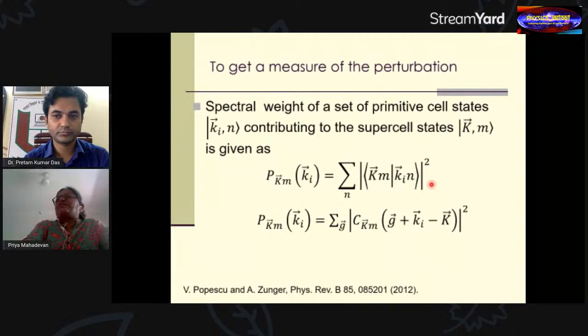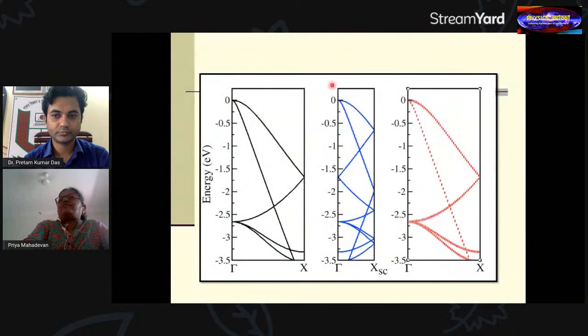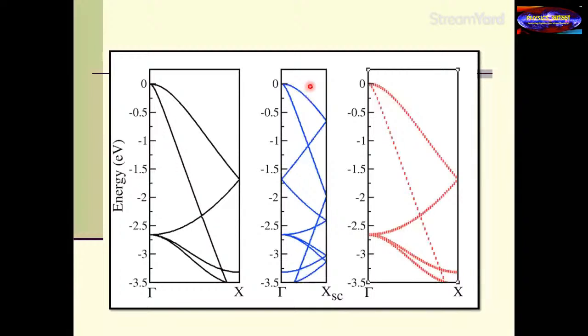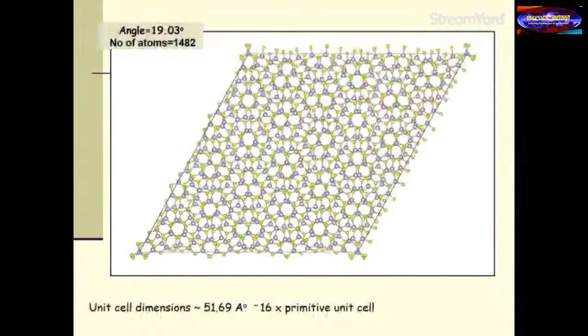Using this kind of analysis, we did the same thing for this band structure, and remember there is no perturbation. Essentially we project the final supercell states onto the unperturbed states corresponding to the primitive cell and recover the same result, which is what we should do. If my perturbation is weak, I can use this method to gauge how much my eigenvalues change. So now we did two test cases over here.